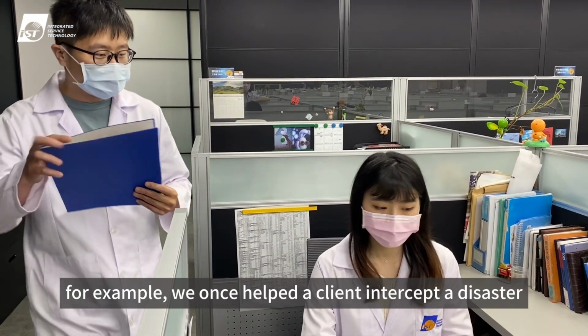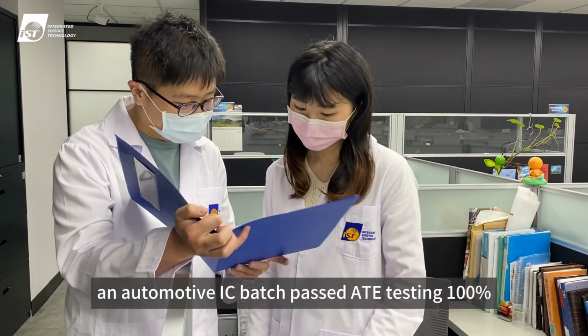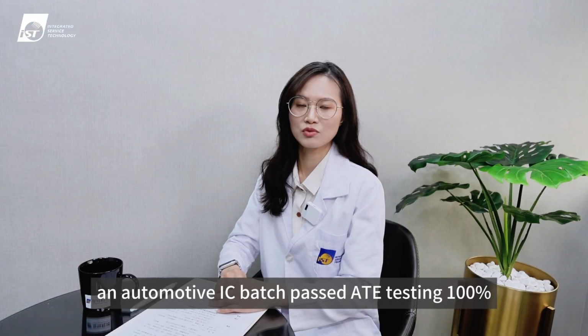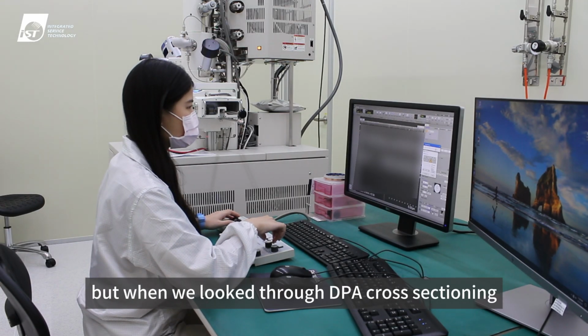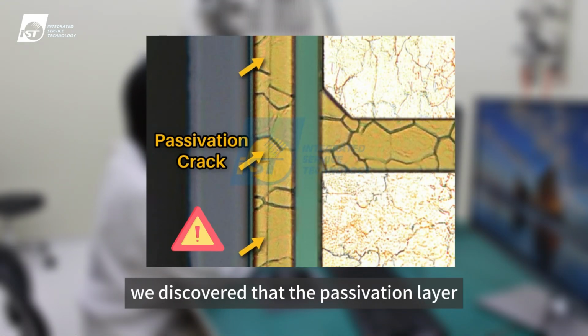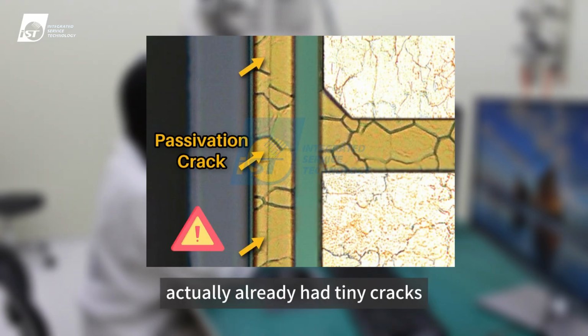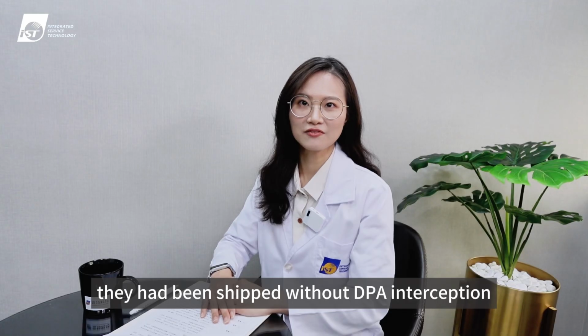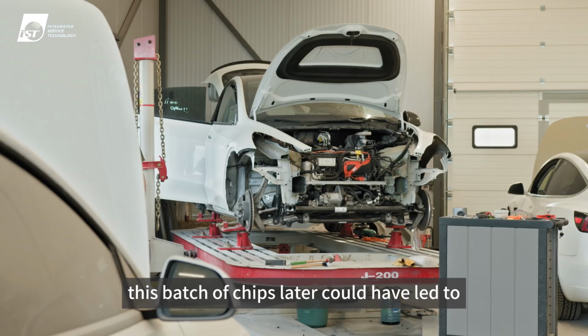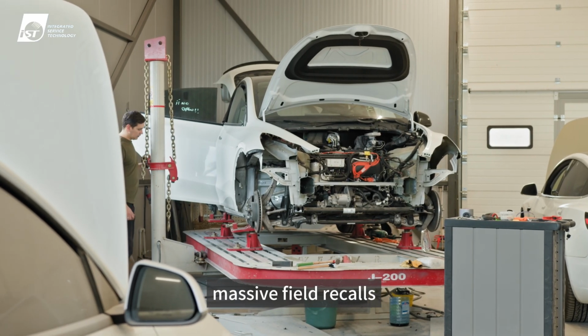For example, we once helped a client intercept a disaster. An automotive IC batch passed ATE testing 100%, but when we looked through DPA cross-sectioning, we discovered that the passivation layer actually already had tiny cracks. If they had been shipped without DPA interception, this batch of chips later could have led to massive field recalls.